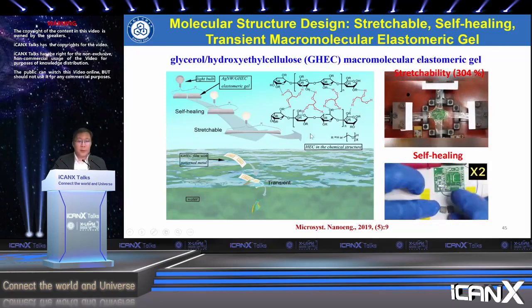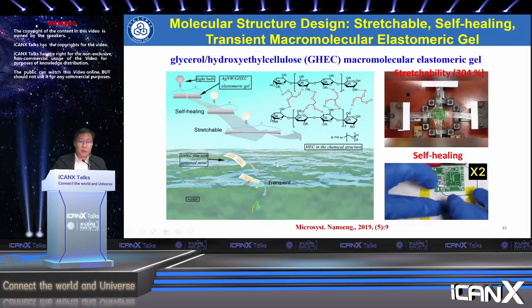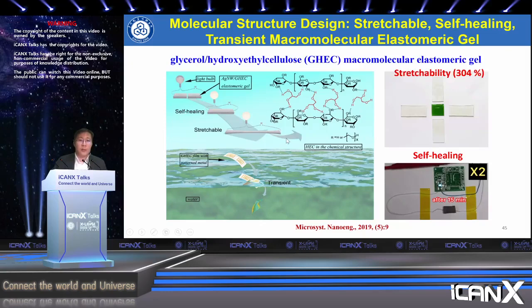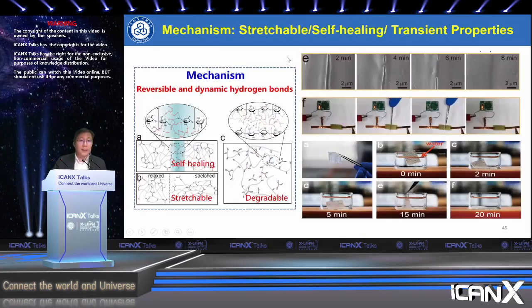And this elastomer gel is totally water soluble, and its degradation rate can be tuned by adjusting the HEC molecules and the ratio of the HEC to the glycerol. So we demonstrated flexible and stretchable electronic devices such as self-healing conductors, and also electronic skin for the robot, etc. And the mechanism is that by inserting the